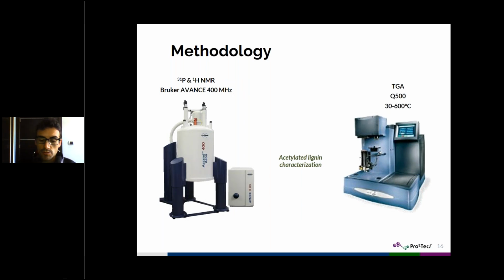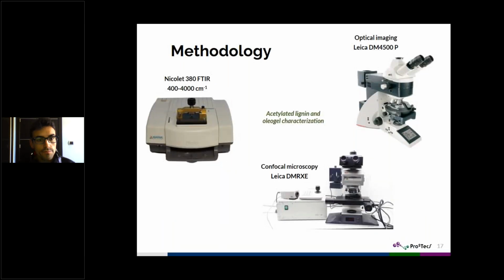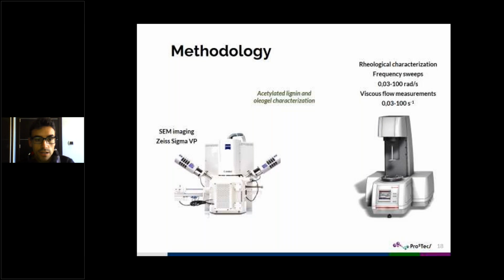Well, for the characterization, we have performed both phosphorus and hydrogen NMR. We have also performed thermogravimetric analysis from room temperature to 600 degrees. We have also performed Fourier transform infrared spectroscopy from 400 to 4000 wavenumber with a resolution of 4 inverse centimeters. And we have performed different types of imaging. Optical, as you can see on the right, also confocal. So for the confocal microscopy, we have dyed castor oil with Nile red. And finally, scanning electron microscopy by using the equipment that you can see in the image.